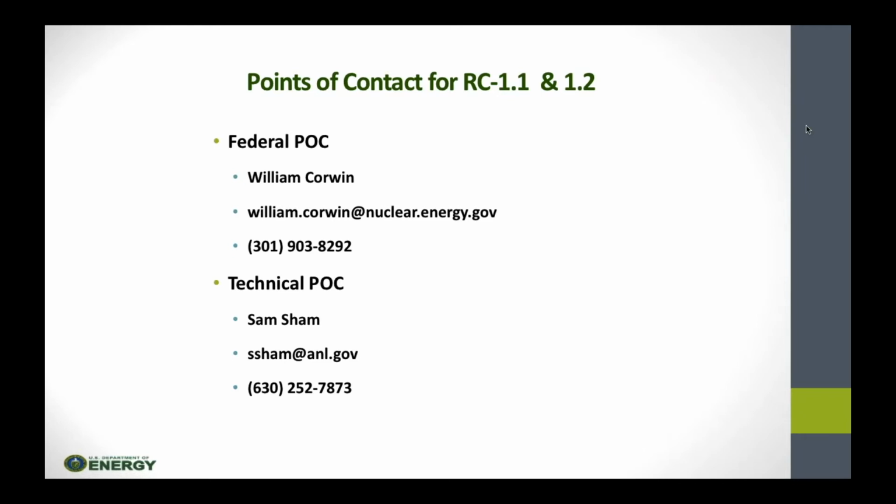They could focus perhaps more on one than the other, but the greatest challenge that we seem to see in this class of reactors is coming up with a material that is adequately corrosion resistant. We have materials that work in the high temperature strength range and that are adequately irradiation resistant for these classes of reactors. But to do that at the same time as having adequate corrosion resistance for the molten salt, we don't have that right now. And so if you can't come up with something that hits all three points of the compass, it doesn't quite get there. So it has to be at least reasonably comprehensive, even if there's one focus area within the proposal.